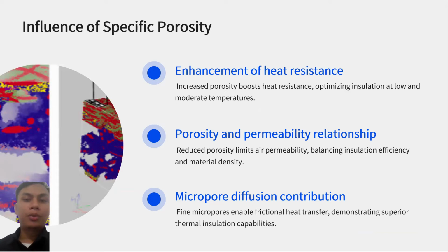Influence of specific porosity. Enhancement of heat resistance. Increased porosity boosts heat resistance. Optimizing insulation at low and moderate temperatures. Porosity and permeability relationship. Reduced porosity limits air permeability, balancing insulation efficiency and material density. Micropore diffusion contribution. A fine micropores enables fractional heat transfer, demonstrating superior thermal insulation capability.